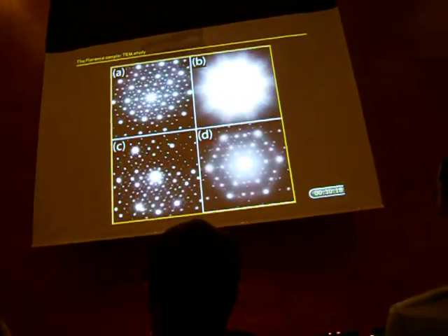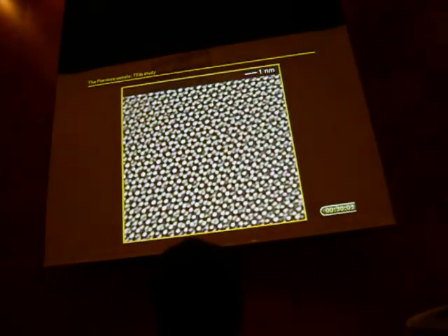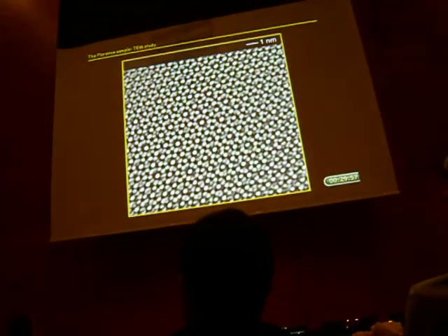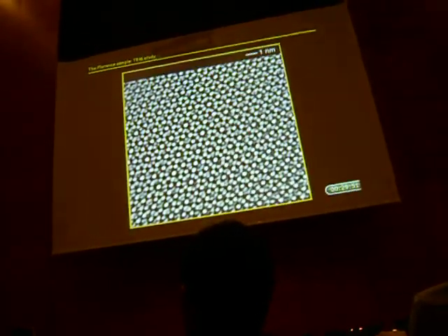At the beginning of 2009, Paul sent me an email entitled 'Quasi Happy New Year.' I immediately realized they had found the last important evidence. Some hours later, they sent these experimental results — really remarkable. They were able to observe not only the five-fold axis, but also the three-fold and two-fold symmetry axes of the icosahedron. They measured the angles of the icosahedron, which are in exact agreement with the ideal angles. Some days later, they sent high-resolution transmission electron microscopy images — which were shocking — showing the overwhelming evidence of atomic-scale icosahedral symmetry with a d-spacing of 5.6 Å in our natural material.